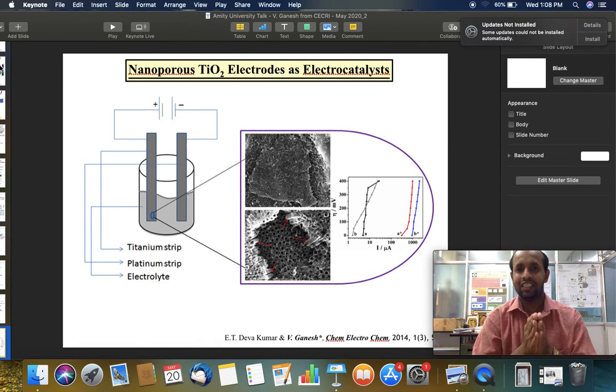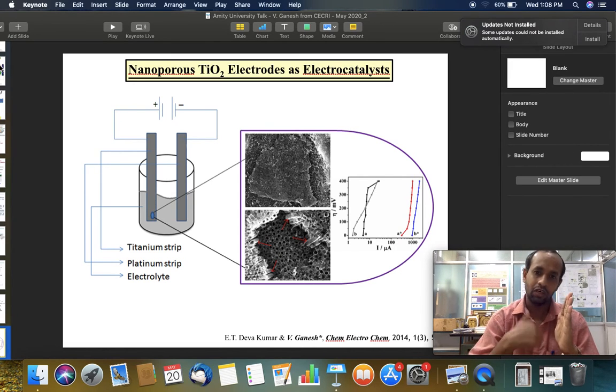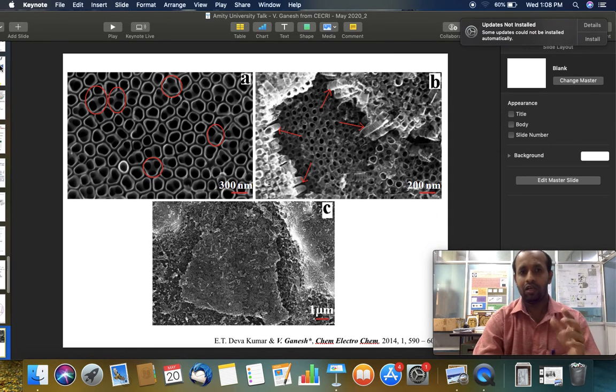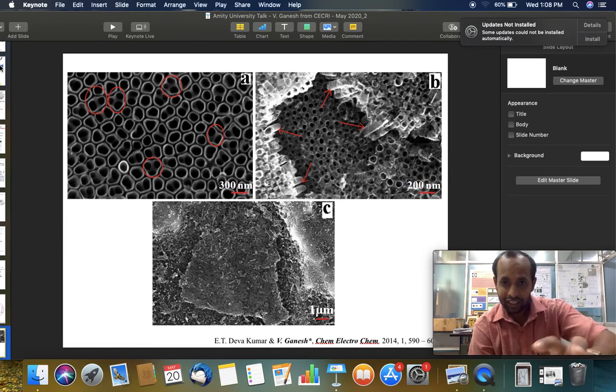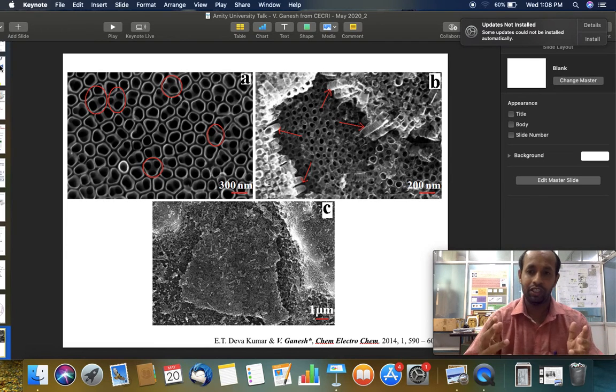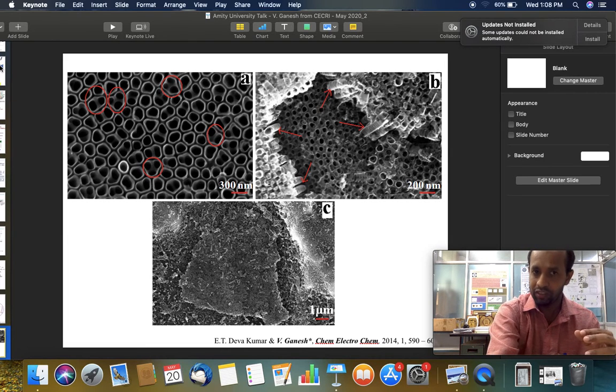In this process, CSIR-CECRI has also come up with many different catalysts. The simple one, again based on a simple electrolysis process, uses titanium as an anode and platinum as a cathode. You do a simple anodization at the titanium anode. Depending upon the variation in the current density and the time duration you allow for electrolysis, you can tune the formation of TiO2 nanotubes, porous TiO2 nanotubes.